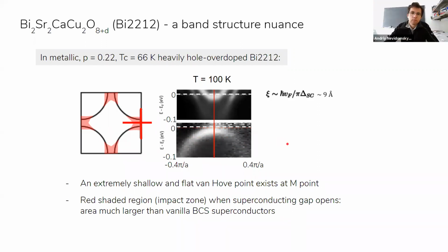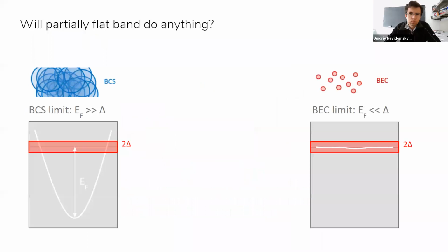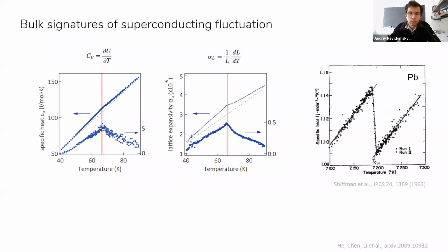Fantastic, thanks. So this kink that you've seen, is that due to electron-phonon interaction or what? Not 1 millivolt. It's about 100 millivolt. Yeah, 0.1 eV. So I don't think that's a result of electron-phonon coupling because the highest energy phonon in cuprate is about 80 millielectron volt. That's right. And sorry, Pengzhi. Yeah, go ahead. It also cannot be due to magnetism, right? I mean, there's no spectral weight, just like as you're saying, right?